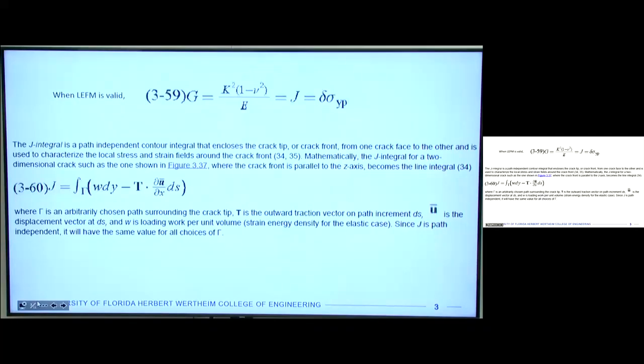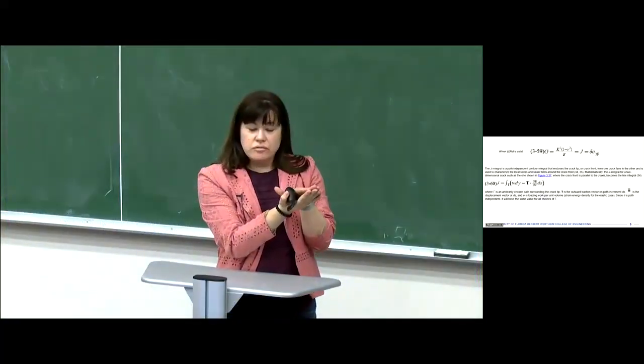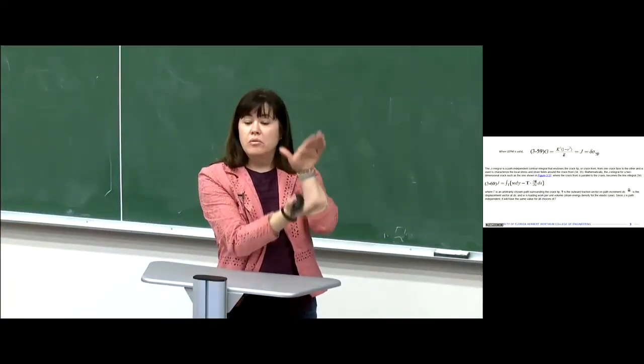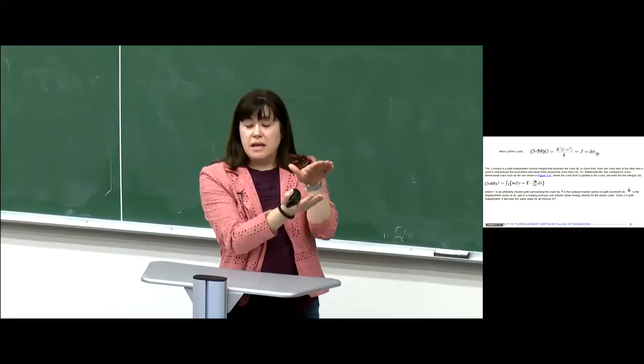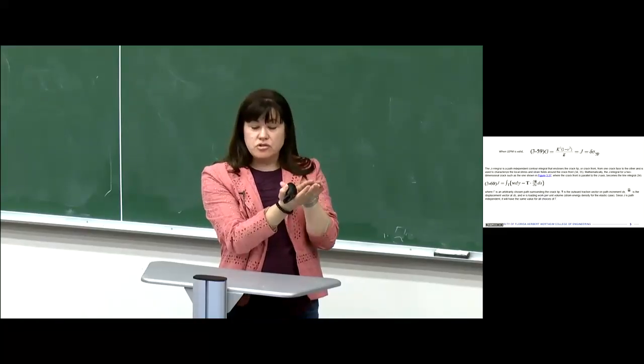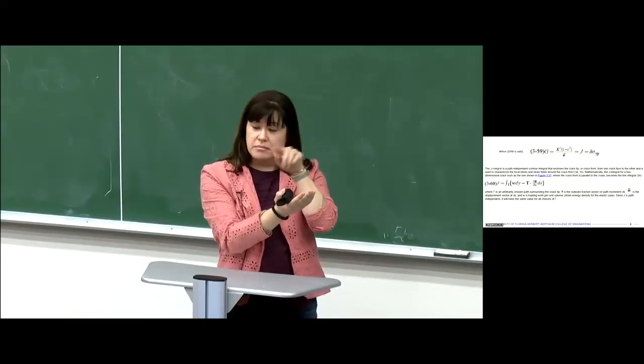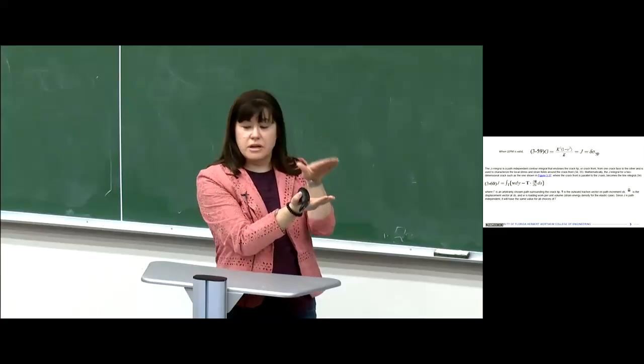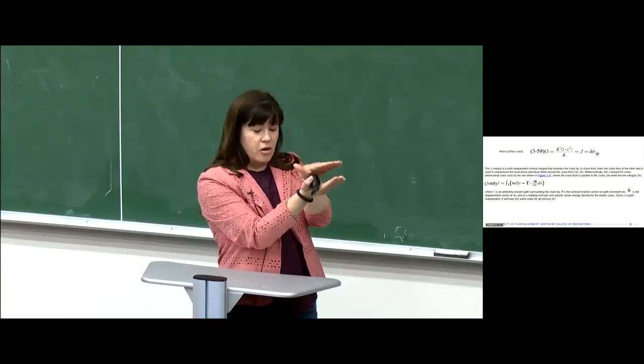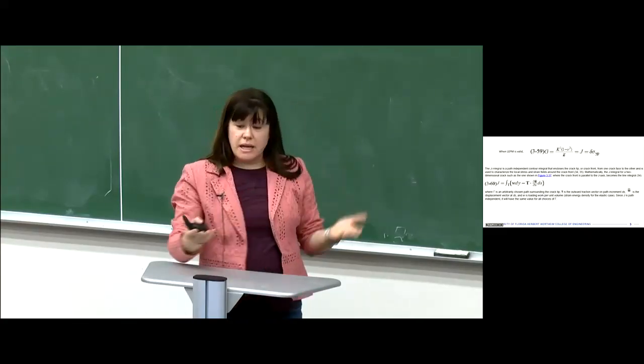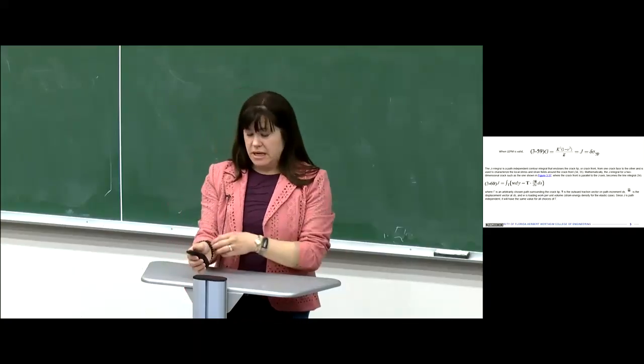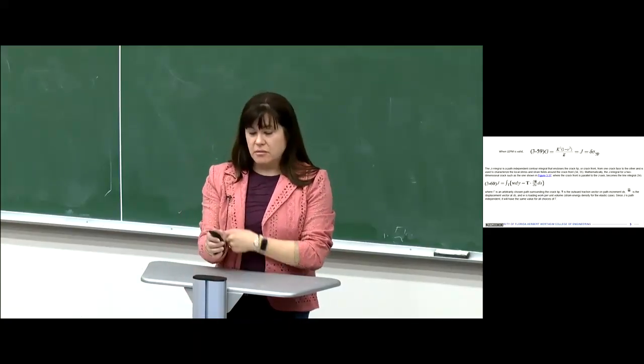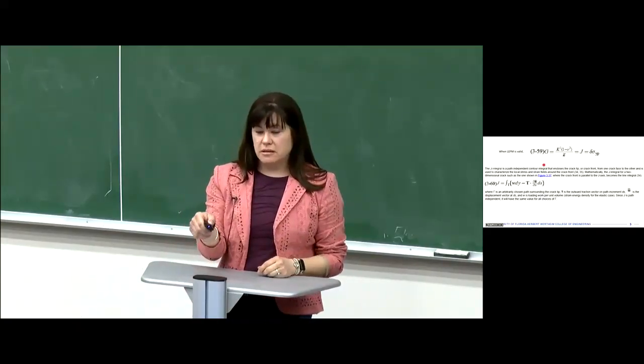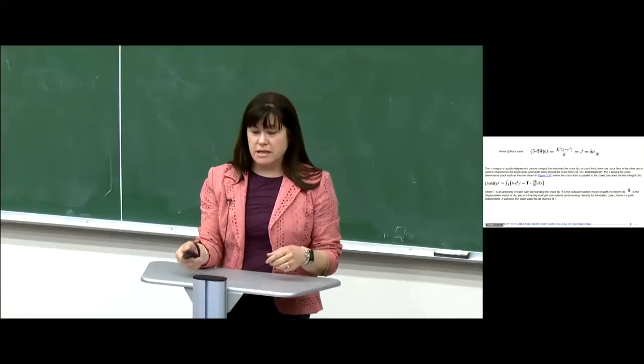And so when there's a crack, so imagine there's an edge crack like we've been talking about in class, and then there's a stress that wants to open that crack in mode 1. Well, there's a strain around the crack tip that exists just because of that stress. And so when the crack opens further, that strain energy is relieved, right? And so that is the basis for this G, this strain energy release rate.